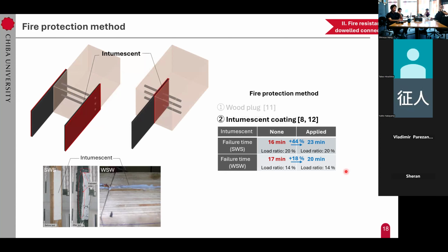Intumescent coatings are another effective fire protection method. When applying them to dowel connections, we typically cover all steel surfaces to minimize heat transfer. For steel connections, the exposed steel plates are coated with intumescent material to reduce heat flux. In wood connections, we usually fill all the gaps where the slotted-in steel plate could transfer heat. Studies have shown that applying intumescent coatings to SWS connections increased failure time by 44%, while WSW connections exhibited only an 18% increase. This suggests that intumescent coatings are more effective in SWS connections where the steel surface is more exposed.